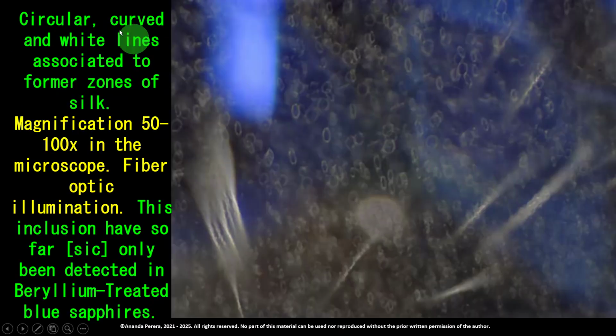Here, look at the circular, curved and white lines associated to former zones of silk. Before beryllium treated, it is a silk zone. But after the beryllium treatment, it's like this. Circular, curved and white lines associated to former zones of silk. At magnification 50 to 100x in the microscope, with fiber optic illumination, you can see this. This inclusion has so far only been detected in beryllium treated blue sapphires.